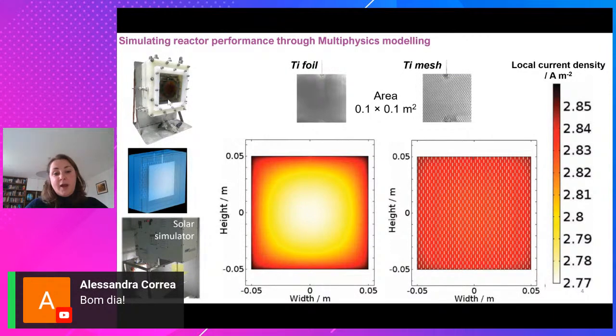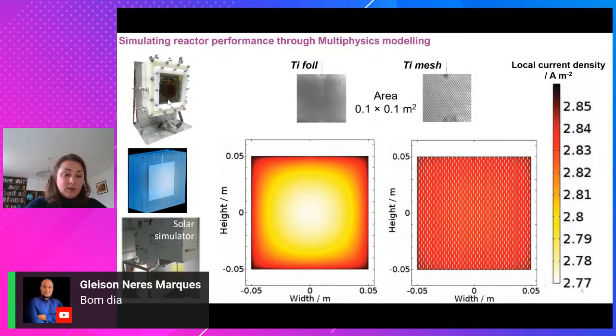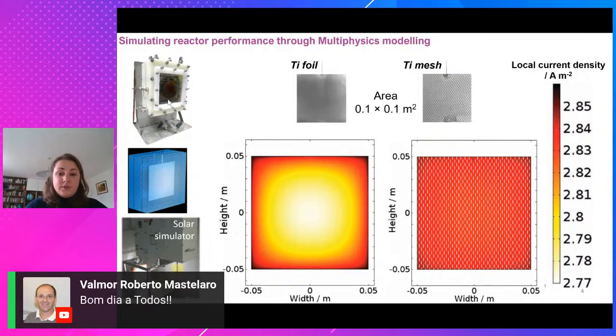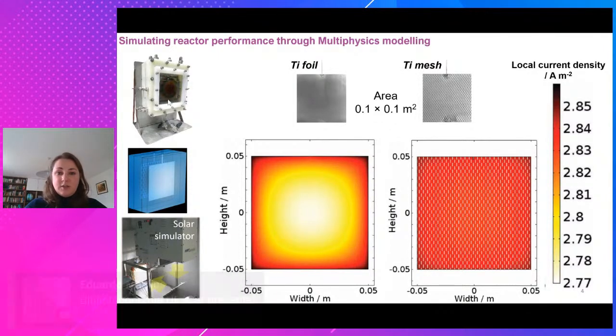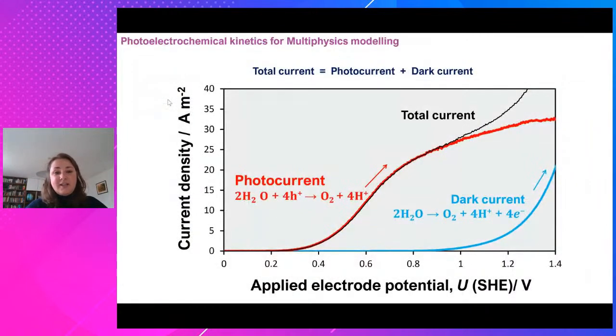The comparisons that we obtained between experiment and the model were facilitated not only by COMSOL Multiphysics, which has a lot of embedded functions, but by accurately inputting the photoelectrochemical kinetics that occurred at the, in this case, hematite-solution interface. So then we come to looking at the details of what happens at a particular electrode when you have photoelectrochemical reactions occurring. This is a case of a photoanode and a comparison of the current density that you get in the case of illumination and in the dark.